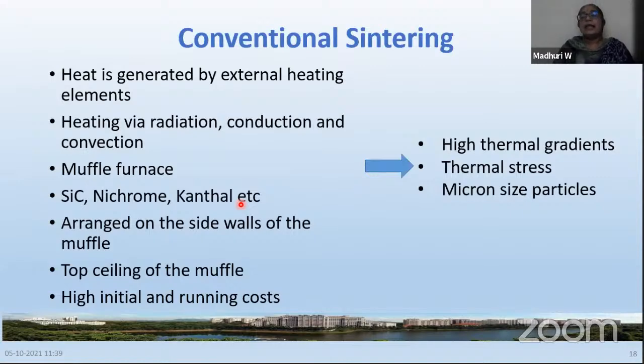But here the problem is, the basic heating is from an outside element. Outside, these rods get heated up, and the heat is slowly absorbed by the material, which is at the center of the box, from the sides of the wall or from top and bottom of the box, whatever is the arrangement. It depends on the time and the temperature, the duration you are keeping it at that particular temperature, how best the material is able to absorb that heat. And what happens, the outer part of the material is taking a lot of heat compared to the central part of the material. Is it not? When you have your heating rods on either side, and you have your material at the center, then obviously the outer surfaces are taking a lot of heat, whereas the central part is not taking the same amount of heat.